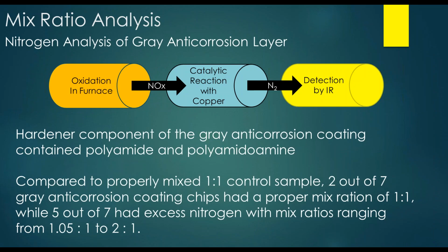The gray anti-corrosion layer, as I previously mentioned, was an epoxy, which was actually a two-part epoxy. One issue that's frequently of concern is the mix ratio. So we used two different methods to analyze the mix ratio of the gray anti-corrosion layer. The first method we used was a nitrogen combustion method. In this method, you take the paint chip and put it in a furnace under oxidizing conditions, which produces various forms of nitrogen oxide species. This is then catalytically reacted over copper to produce elemental nitrogen, which can then be detected by infrared spectroscopy.